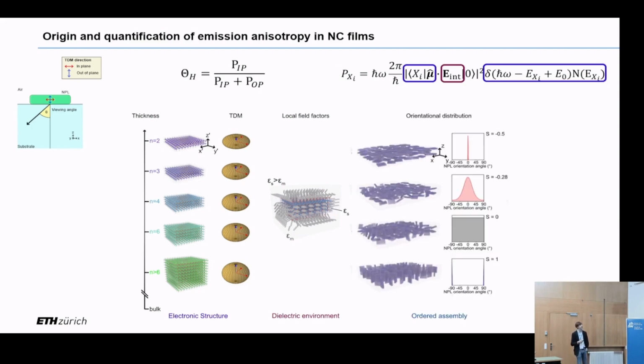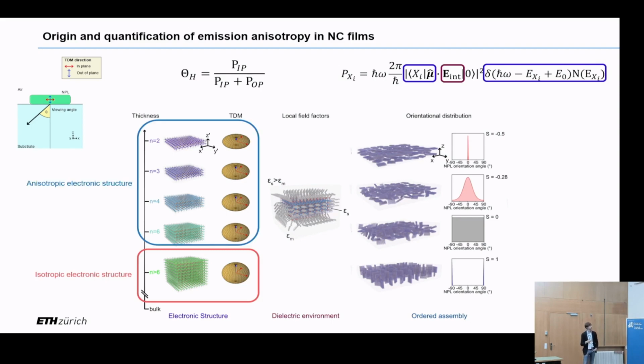And third, of course, let's suppose we have such a nanocrystal which has an isotropic TDM orientation. In order to achieve emission anisotropy from the film, we need to control how the single nanocrystals assemble together in the film. They need to preserve the order by assembling in an ordered manner. I will present briefly two, let's say, case studies.